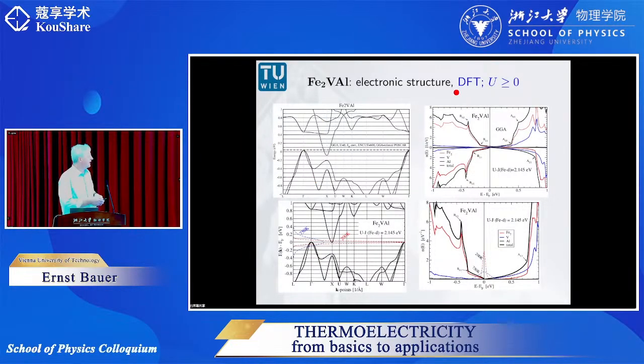So what we have calculated, for example, in the case of Fe2VAl, is a so-called full Heusler compound. You can see here the dispersion in several high symmetry directions, and here is plotted the energy, and at 0 we do have the Fermi energy. You can see from these results that at the gamma point of this material, the valence band touches almost the Fermi energy, and at the X point, the conduction band is slightly below the Fermi energy. So if this calculation is true, then this would be a typical example of a semi-metal.